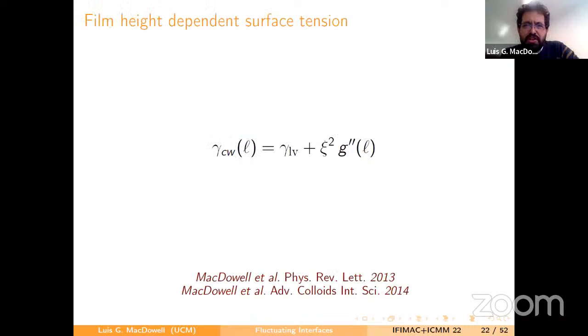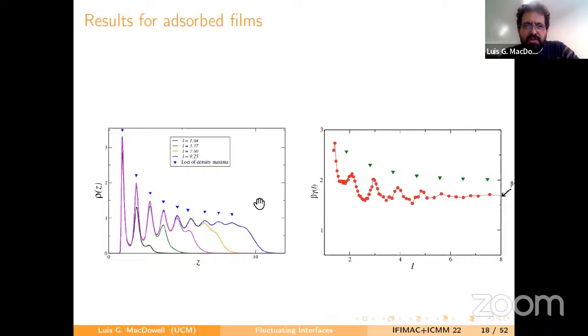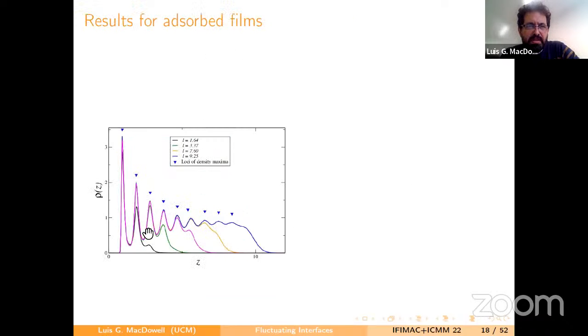It's a good point, and actually you're right. Yes, eventually, if you have a very stratified film, then when the film is thin enough, likely you have anisotropy. Well, let me think. It depends on the structure of the layering. But it's true, one should study both fluctuations in two different orthogonal directions, and it would be interesting to study whether there are differences. Anisotropy in cubic crystals or in close-packed crystals is usually anisotropy even in layered films. I think the free energy of a surface should depend on its orientation if the fluid is layered.